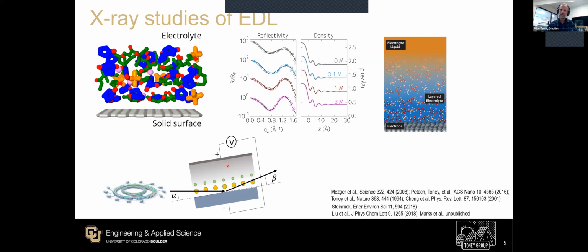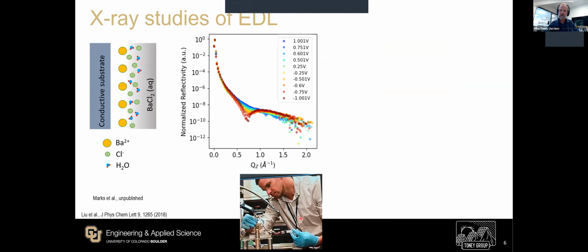Of course, that's not really electrochemistry because the surface is insulating and we can't really apply potential. So recently we've done some experiments, led by Sam Marks, a picture shown here at the ESRF, where we're adopting a conductive substrate. In this case, I'm showing you some barium chloride electrolyte. And here's a hypothetical arrangement of the cell as we bias the potential negatively. This is now a reflectivity curve as a function of potential from about 1 volt down to about -1 volts. And you can pretty clearly see a strong change in the reflectivity, which is a manifestation of the details of what's going on in the electrochemical double layer.